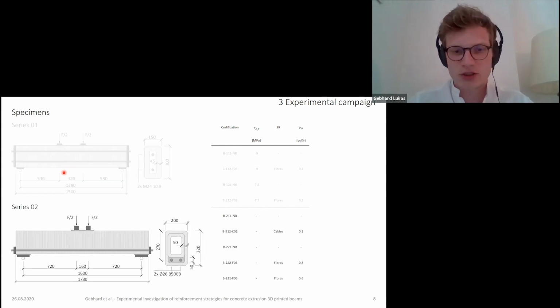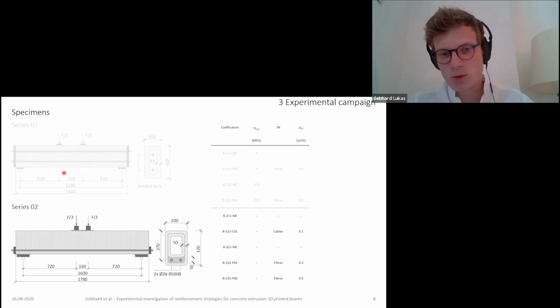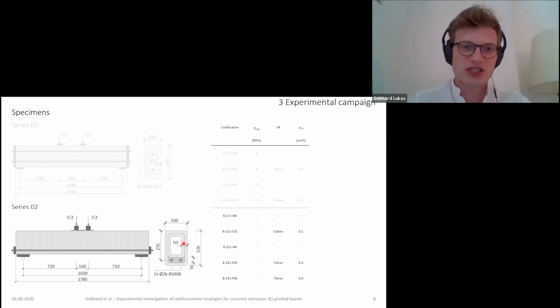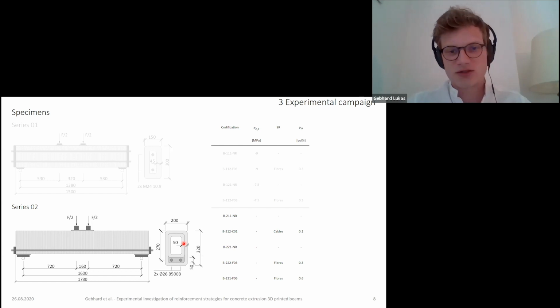The second series used the conventional passive reinforcement with the grouting, so bonded passive reinforcement. We produced 5 beams. We produced 2 unreinforced beams, 1 beam reinforced with cable reinforcement as transverse reinforcement, and 2 fiber reinforced beams. And here one of the fiber reinforced ones was 0.3% and one 0.6%. And as you can see, the cross-section is slightly increased for these beams. So here we had 32 times 20 centimeters, and we printed 2 filaments, not just 1. And also the span was increased to 1.6 meters.